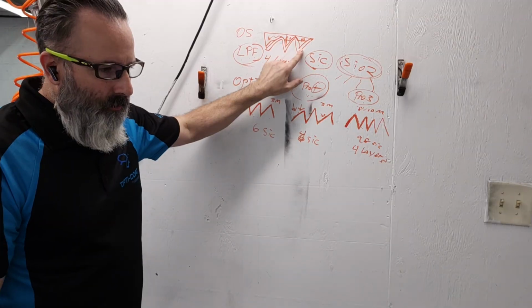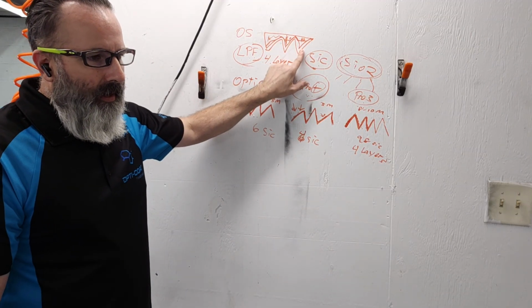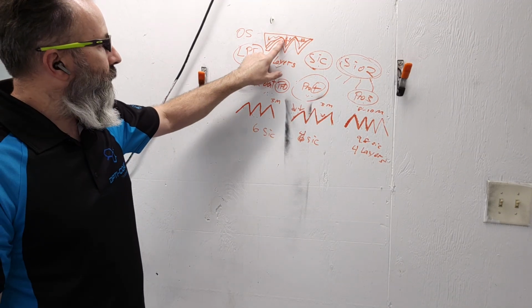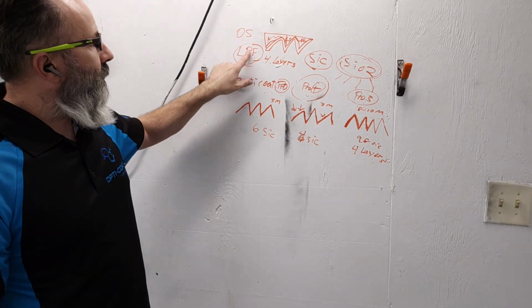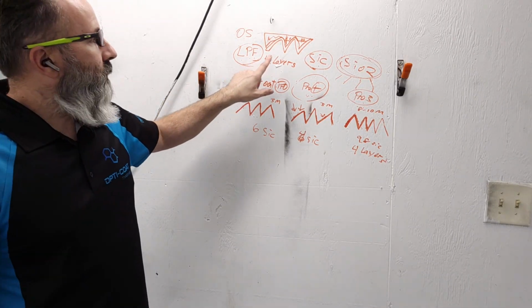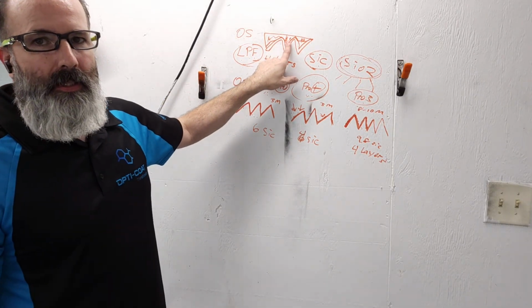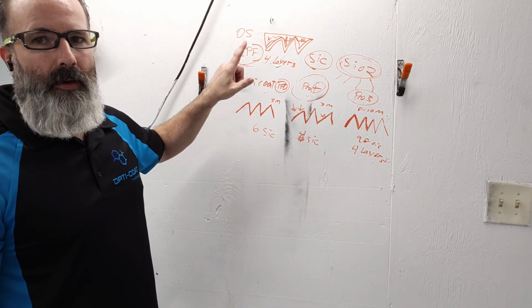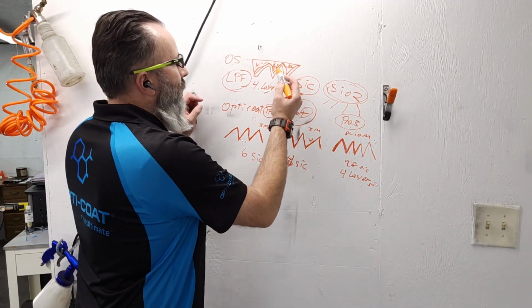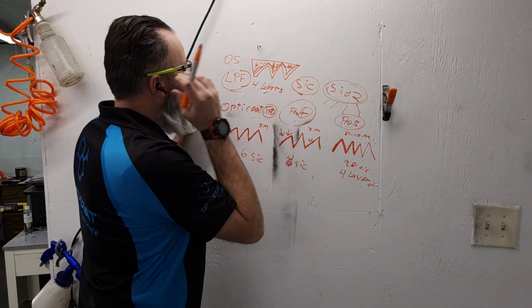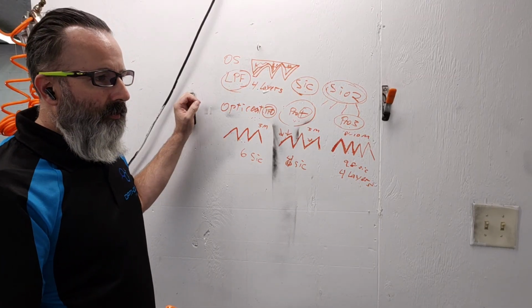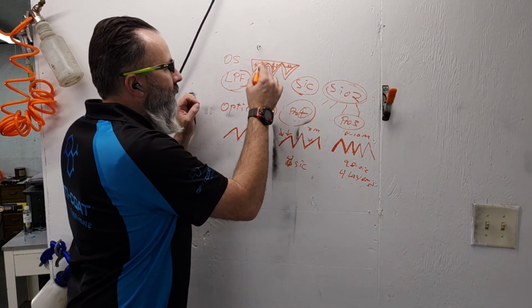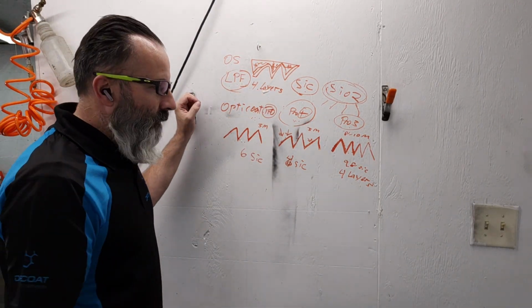So how much clear coat do we have? About 1.5 mil, or 40 microns. We have 30 microns of Opti-Coat, our liquid protective film. So it's almost as thick as the factory clear coat. Now, keep in mind that not only is it almost as thick, it's so much harder than the factory clear coat. It's also self-healing. It also adds a ton of depth and gloss.